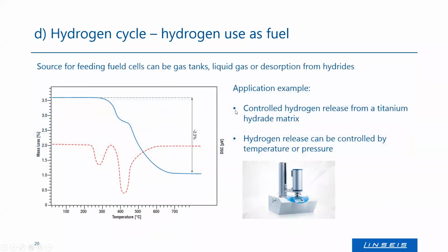Yeah, we have another example here, which is desorption. That's what I was missing 2 slides ago. So this is a controlled hydrogen release by temperature, where the hydrogen was adsorbed in a titanium matrix. And as you can see, you can desorb hydrogen temperature controlled in a 2-step process from this titanium surface, making a constant hydrogen release possible.